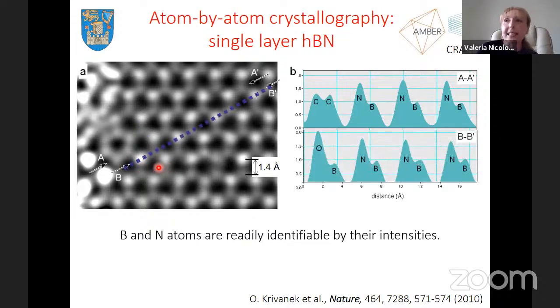So again, if we take an intensity profile, we could see that is a boron, nitrogen going all the way down until we hit this atomic species here. And this is the intensity that corresponds to it. And it's much heavier than nitrogen, and is actually oxygen here. So again, we created some oxygen inclusions in our lattice.